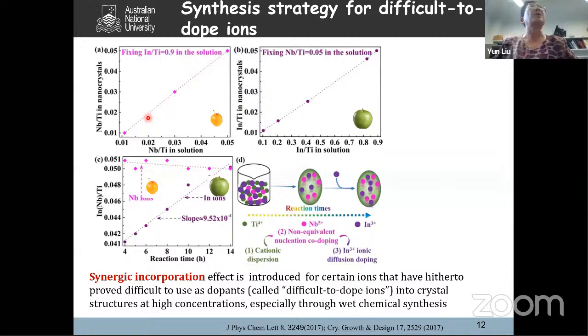interacting. So this is niobium. If we put in a certain niobium concentration, you can see from here with the reacting time, niobium can immediately reach your expected doping level. Okay, so if you want 5% niobium, you just put in 5% niobium, and you get it. So this is an easy doping ion. For indium, if you want 5% and put 5% in the solution, you never get it, no matter how long the time.